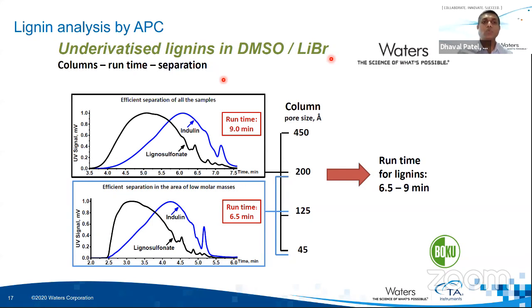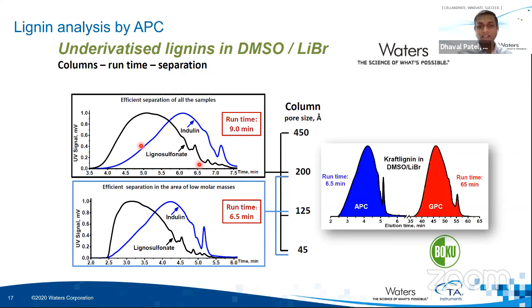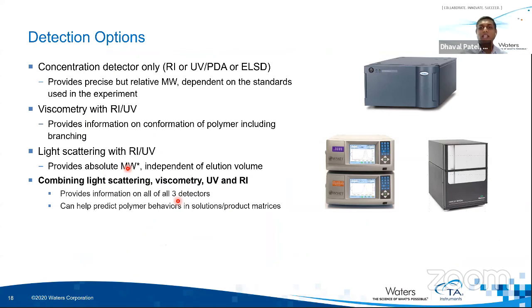So what they were able to do, by a combination of 3 or 4 columns in a row, as you can see here, is achieve a very good separation of low molecular weight species, all the samples in a single run. So why am I showing this diagram? Because originally they were running what we call a 65 minute run time in their GPC method. When they moved to advanced polymer chromatography, they realized that this technique is not only fast, but it gives them a better separation so that they are able to see more characteristic features of the polymer, which they were not able to see before.